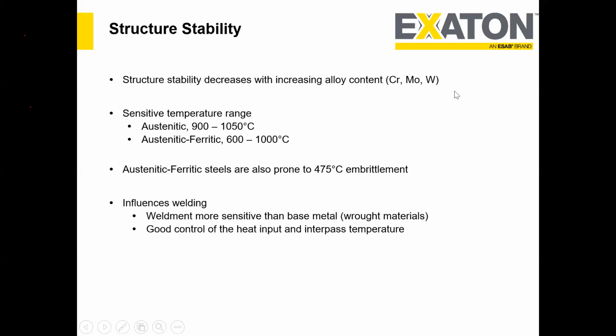So what does it signify? The higher the grade of the duplex family, the more challenging it is to get a stable structure, stable in terms of being without intermetallic phases or undesired structure. There is a sensitive temperature zone for the austenitic phase of 900 to 1050. Duplex is more sensitive, around 600 to 1000. You have probably heard of sigma phase and chi phase. These kinds of detrimental phases form within this temperature zone. I will show this later.